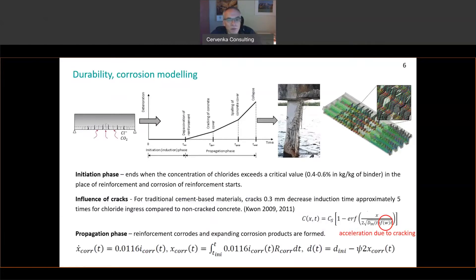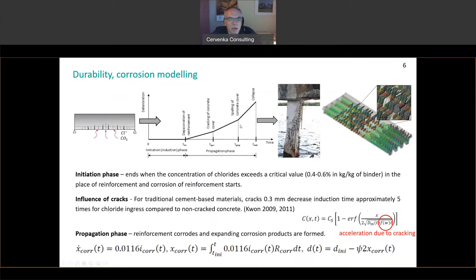An important durability issue for reinforced concrete is the corrosion of reinforcement. Our durability model identifies the key phases: first, the initiation phase — the time needed for chlorides to propagate and reach the reinforcement depth. At that point, corrosion starts and we can then identify the following phases when the reinforcement cover cracks and when it is totally separated, so-called spalling. Each of these phases increases the rate of corrosion.